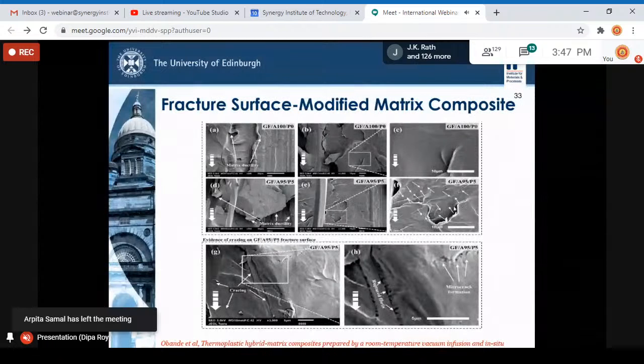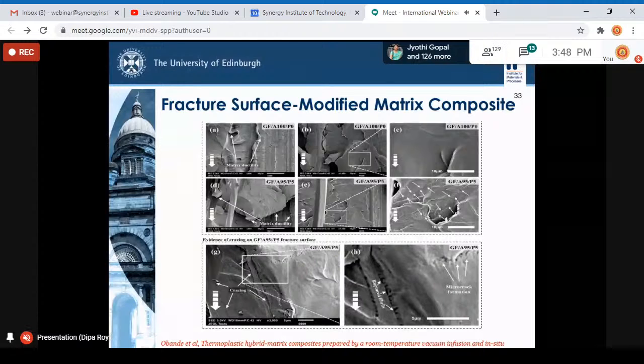So under fracture, when we did some flexure testing, there was a lot of fibrillation in the matrix. The behavior of the matrix was quite different when this PPE was incorporated in the system. Some difference was expected, and a lot of energy was absorbed in this fibrillation as well. Overall, the energy required during the fracture was quite different in the case of the modified composite.